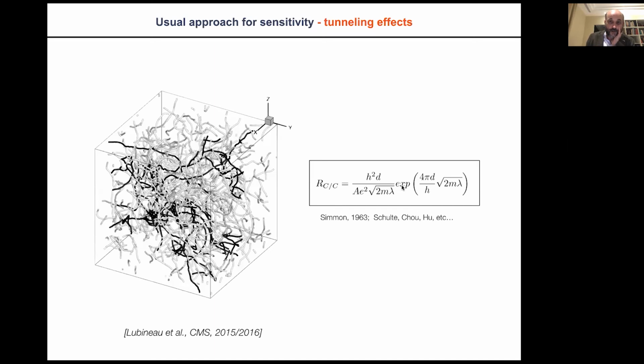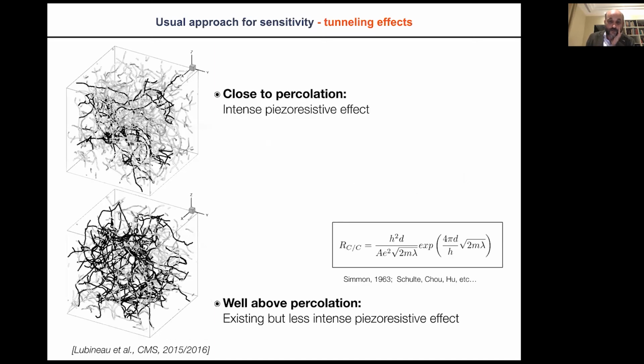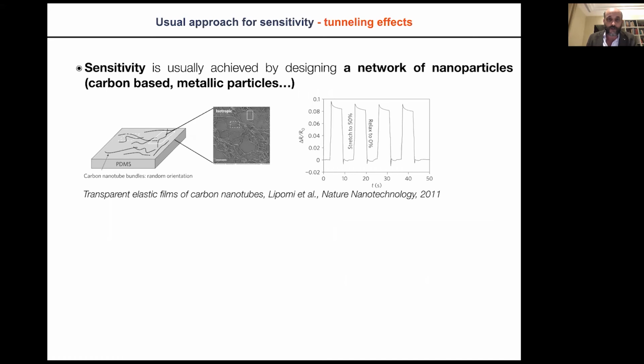But this is something that is not going to be so sensitive, because it is very sensitive when you are close to percolation. But as soon as you have a well percolated network, you lose a little bit of the sensitivity. And you have a piezoresistive effect that is not so big, so it's difficult to sustain a high gauge factor. So what we did in the team is to say, okay, when you look at the technologies that are using this, usually the gauge factor is relatively limited.